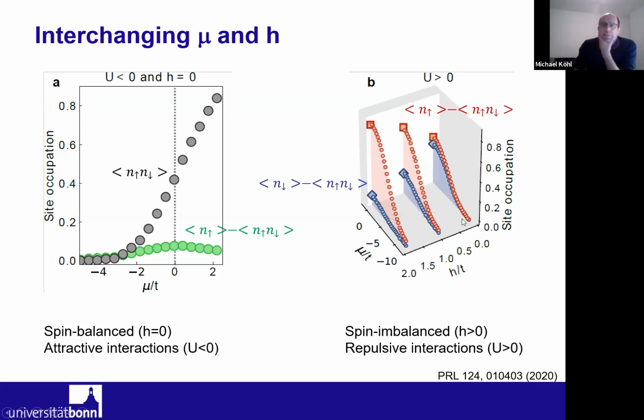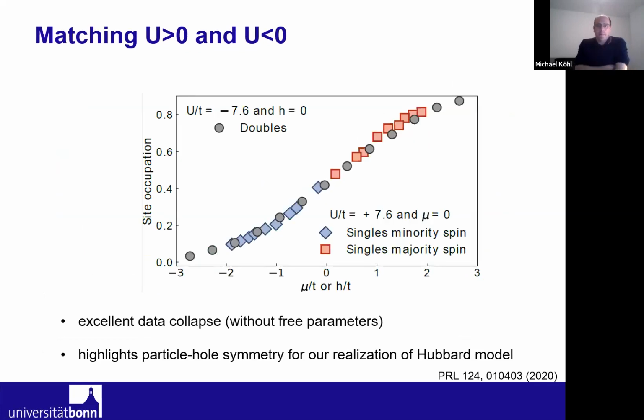Now, what we're interested in is finding out what is the chemical potential. And what we basically do is we measure for the 2 different spin densities the corresponding chemical potentials here and here, here and here. And now we want to map that information to the spin balanced case. So now we take all of this data and plot this onto one graph. And on the one hand, for attractive interactions, we plot the doubles density as a function of the chemical potential. And for the repulsive interactions, for the exact opposite value, we plot now the density at chemical potential equals 0 as a function of h.